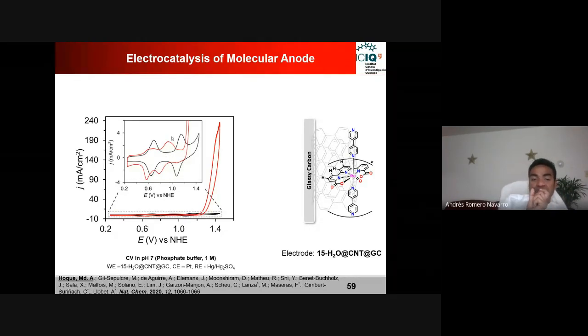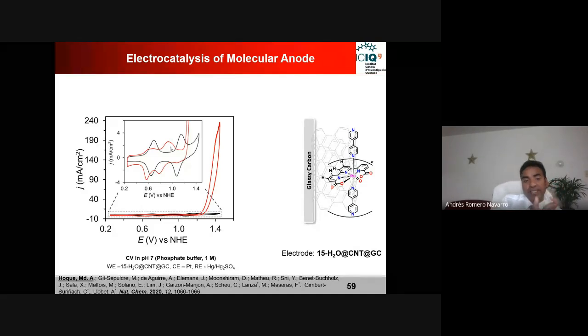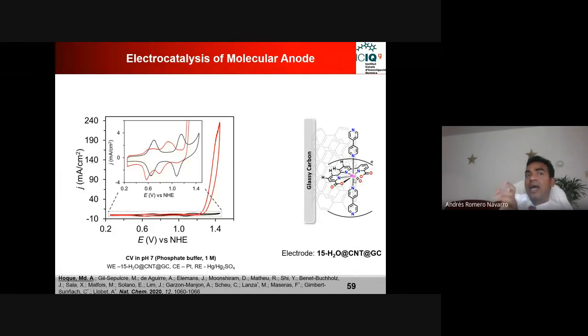And these are pH dependent, which is suggesting that your metal is coordinated with the water, and depending on the pH, your water can be protonated or deprotonated. So that is very strong evidence that we have this catalyst.